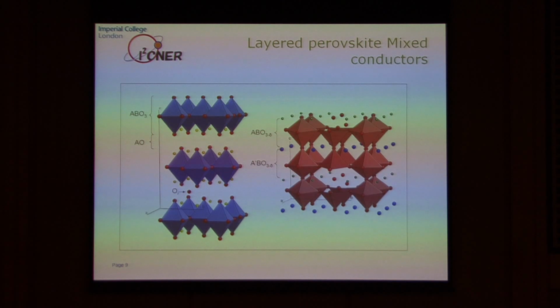Just before I finish, an example of the materials we've been thinking about: mixed conducting materials used as electrodes in these cells. These are Ruddlesden-Popper phases, consisting of layers of rock salt and perovskite structures - almost two crystal structures placed one on top of the other. This is an example of two perovskite materials with high oxygen mobility at low temperature, perhaps because I believe they are natural nanostructures - nanostructures that nature made rather than man-made structures.